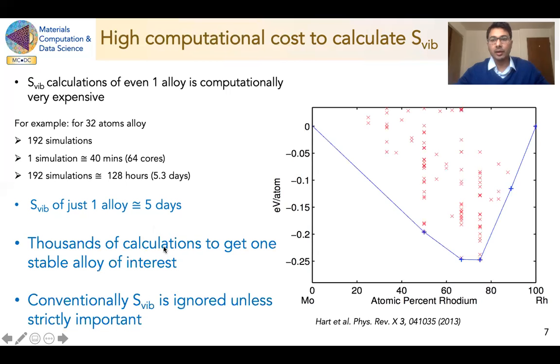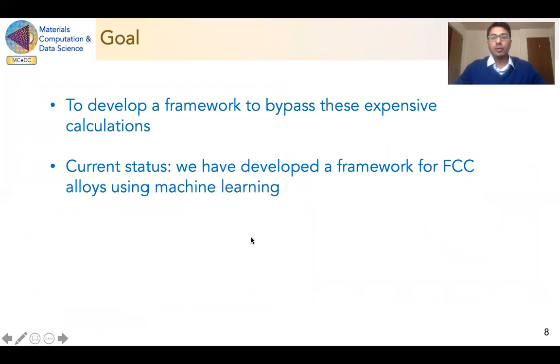Now, to find one stable alloy, you have to study a lot of compounds and alloys. As you can see in this phase diagram, to get this lowest energy structure, you have to perform all these calculations, which are shown in these red dots. Now, to calculate vibration entropy in all these alloys, it requires thousands of calculations, which is a very difficult task. Thus, there is a need to develop a framework or a strategy that can bypass these expensive calculations. So our goal is to develop a framework which can bypass these expensive DFT calculations. And our current status is we have developed a framework for FCC alloys using machine learning.